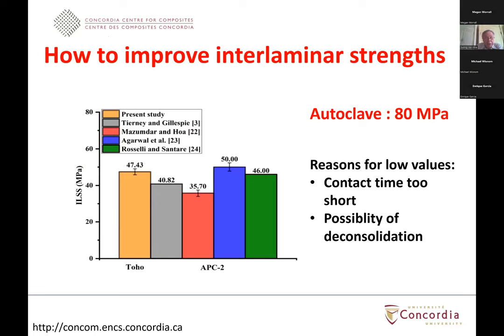The other thing about the processing of automated fiber placement using thermoplastic composite is low interlaminar strength. Now there has been a lot of work done and people have measured the interlaminar strength for the thermoplastic composite, take carbon PEEK using AFP. And the value they obtain is between, say, 35 to 50 MPa. Now if you do that for the autoclave, you get 80. So there is a big difference between the interlaminar shear strength for the case of AFP and autoclave. And there are many reasons for these low values.